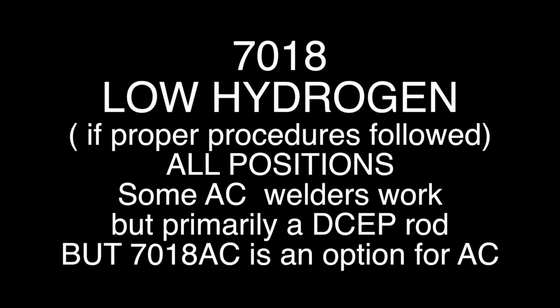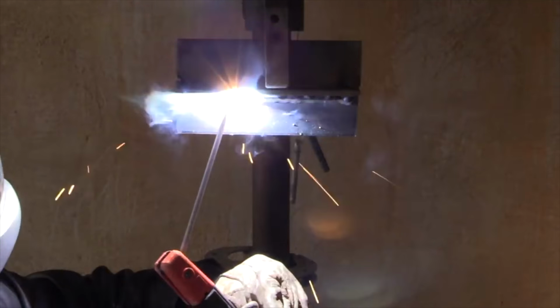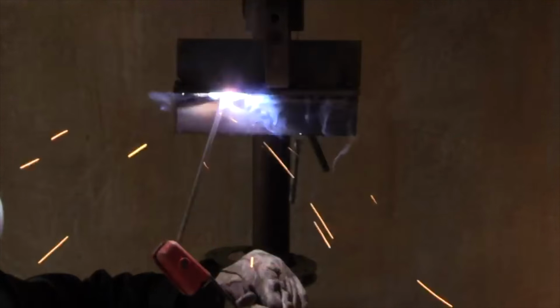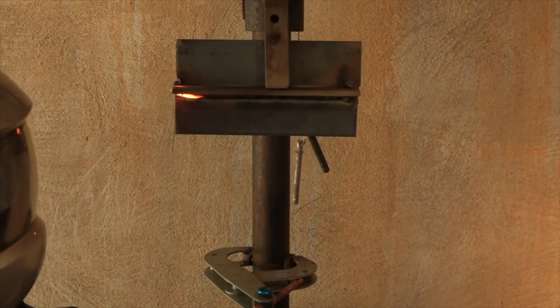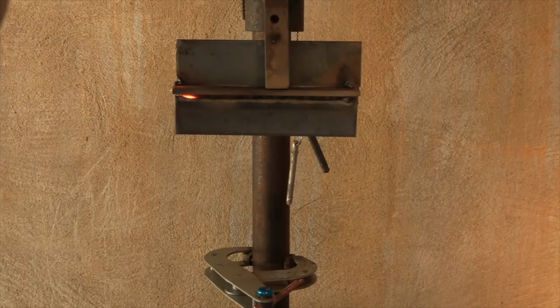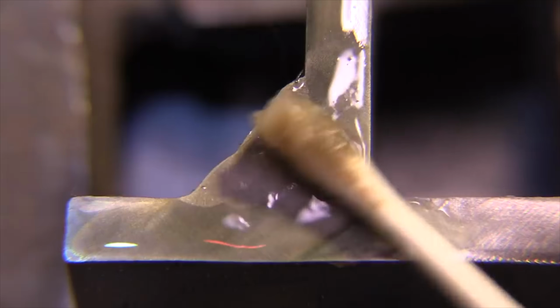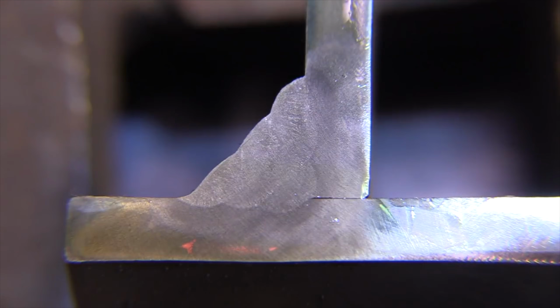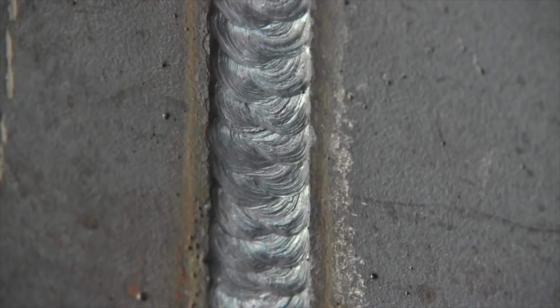7018 electrodes are classified as low hydrogen electrodes. They are the backbone of the construction industry here in the USA anyway. And they're all position, so overhead welds like this are no problem. The best technique I have found is to weld with the same heat, maybe a little bit less than I would flat. Hold a tight arc, don't get carried away with too much angle. Set the machine hot enough where when you hold a tight arc it won't stick, then hold a tight arc. That's the best advice for overhead welding I could give anybody. And a nice quick cut and etch test will eliminate any doubts on your settings or procedure.